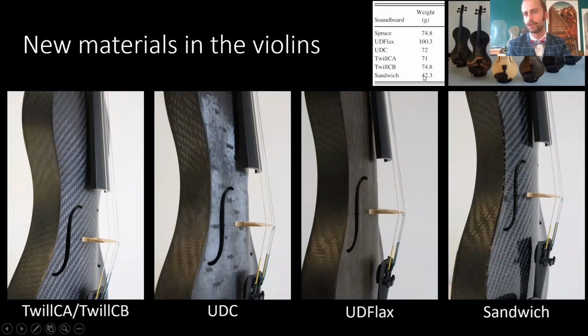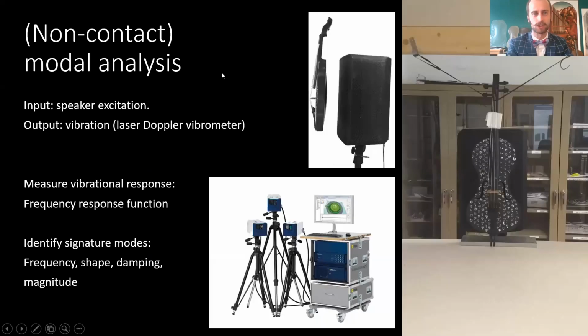So for all of these instruments, it was the weight of the soundboards just before they were glued. The ends were trimmed off a little bit, so it could be that the end weight is a little bit lower than what's here, but it will not be so much. So like this, I have made 6 violins. And I wanted to see now if we can see the effect of the weight, of the different anisotropy, of the different fiber on the instruments, and if we can measure the change.